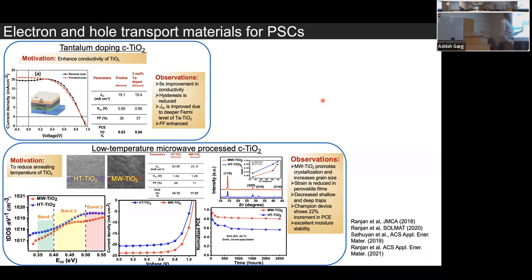Another thing we see is that when you process TiO2 using the microwave process, the grain size of perovskite on it is very large, which leads to lower recombination in the device. Microwave TiO2 also leads to better texturing of perovskite thin films. Based on our electrical and optoelectronic measurements, we find that the defect density in microwave processed TiO2 is lower. So overall, the efficiency is better and stability is slightly better. It's not very highly improved.